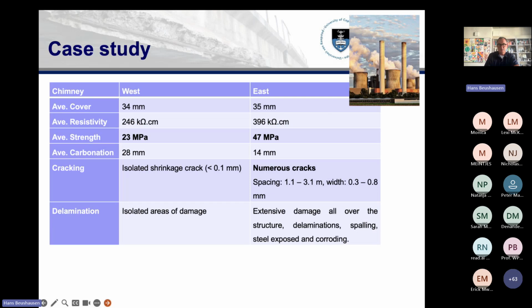They had different resistivities, which link to the different strength. Resistivity is a measure of how fast electricity can flow through the concrete. And typically, higher strength concrete gives you higher resistivity, which also gives you a higher resistance against reinforcement corrosion. So the West Tower, having 23 MPa, had a lower resistivity compared to the East Tower, which had twice the strength and also higher resistivity. The carbonation depth measured on the West was much higher than the East, which is because a more dense concrete, the 47 MPa one, will carbonate slower. So that's good. But at the same time, the high strength chimney was full of cracks. Cracks were all over the place, with crack spacings of around 1.1 to 3.1 meters and crack width up to about 0.8 millimeters.